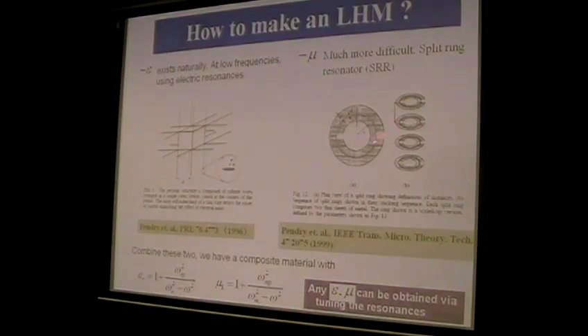The current will have a very strong magnetic resonance, so that the system can behave like a magnetic resonator. If you combine this structure and this structure, and if the wavelength is still much longer than the feature size of these structures, the system can be homogeneous, just like the concept of a metamaterial. Then the composite material will have an effective epsilon like this and an effective mu like this. If you can carefully tune the resonance frequency of the electric resonance and also the magnetic resonance, very possibly we can have a common region where both epsilon and mu are negative. That's the region where we have the left-handed material.